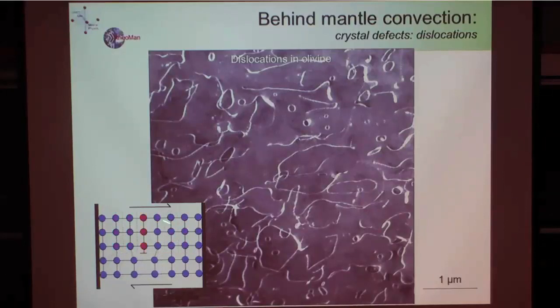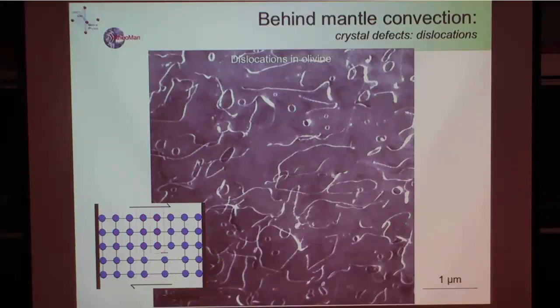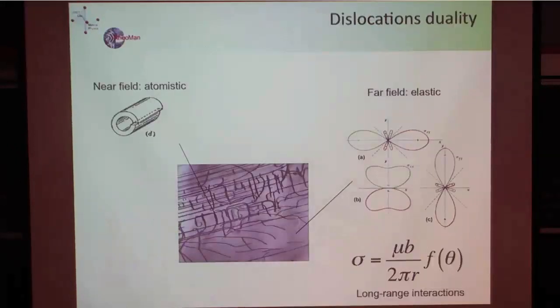This is basically the idea. This is the process. The dislocation can glide in a specific plane, and the idea behind a dislocation is that you're not just brutally breaking all the bonds at once, but you do that bond after bond, you localize plastic shear, and then you propagate plastic shear. This is why this is a transport property, actually. So this is the idea behind dislocations. Those lines move through the crystal, and this is how you get plasticity.